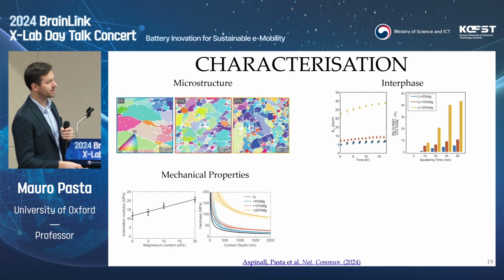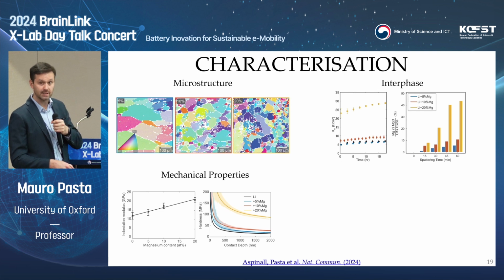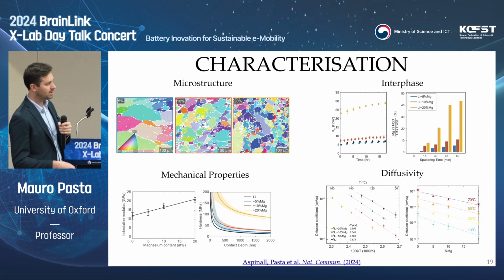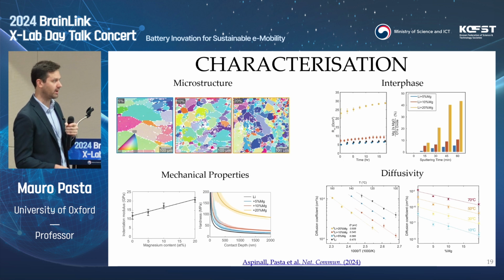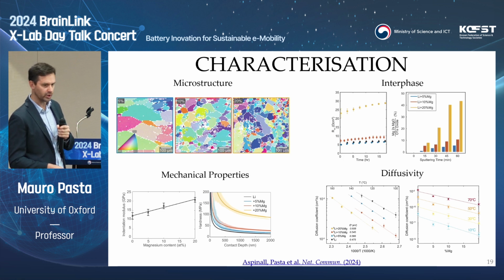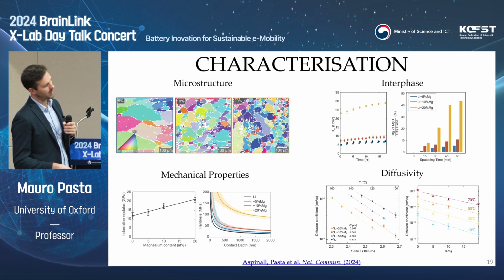And you can do that by using electrochemical impedance spectroscopy in a 2-electrode, 3-electrode system. We can do XPS and characterize the chemical composition. And you can also measure the diffusivity as a function of what you're adding in there. And again, we're using solid-state NMR in here because it's quite convenient. You make your alloys, you use solid-state NMR with lithium-6, and you quite rapidly get diffusivity and activation energies that allow you to extrapolate over a different temperature range.